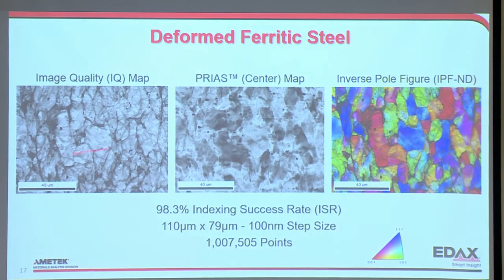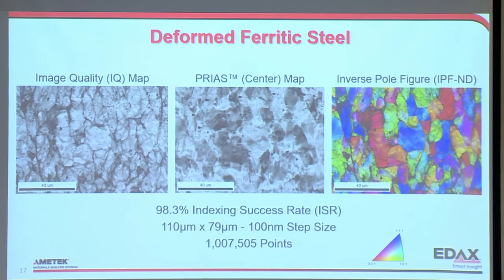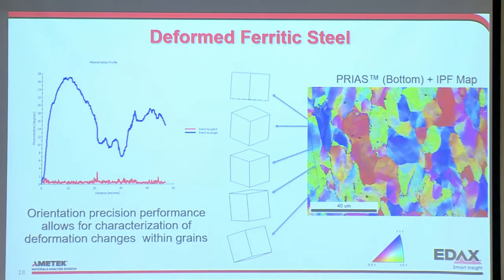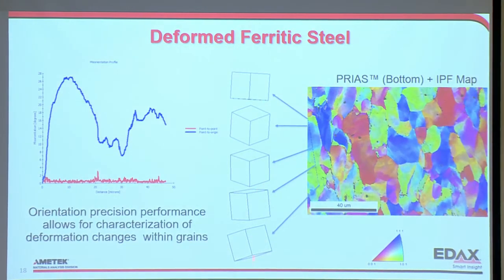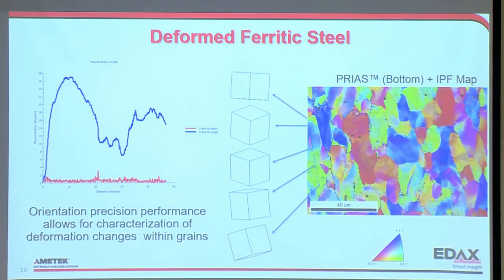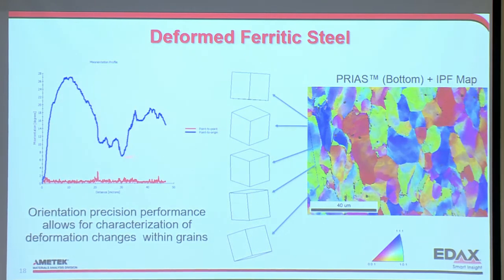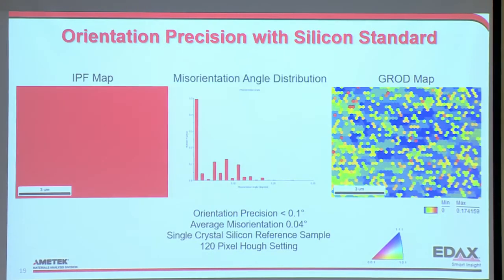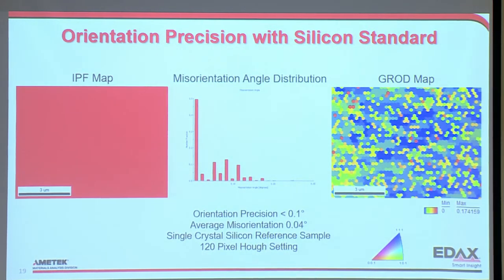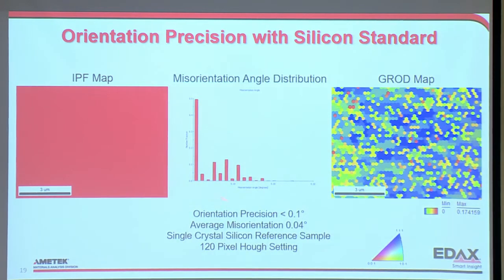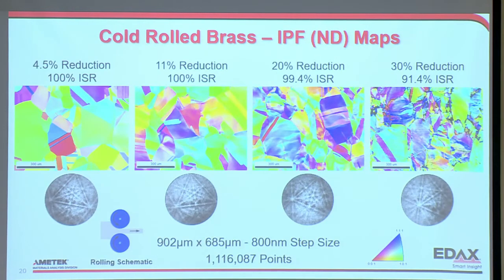Here's a deformed steel, just to show you can deform metals even though we have the higher beam currents. We still get great indexing success rates on this. This is 1 million data points. And just to show we do capture the subtle changes in orientation, even at these high speeds, this is within this 1 grain here, and you can see we are capturing these low angle misorientations. The orientation precision is very similar to what we do with the CCD cameras. In this case, we've got less than 0.1 degrees. The average misorientation in this maybe 10 micron by 10 micron scan is 0.04 degrees, which is terrific. And that's partly because we're working at a little higher resolution.